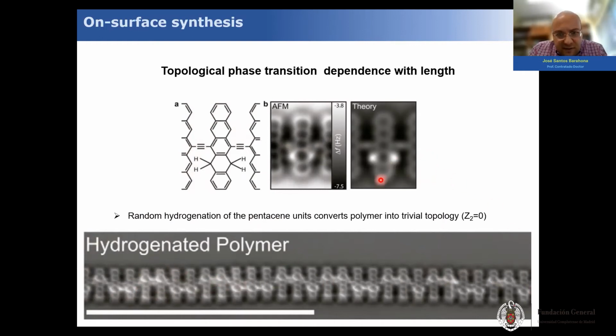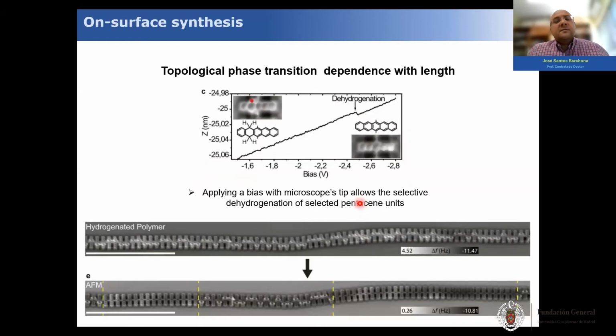As you can see, the hydrogenation is denoted by these brighter spots here, because they are no longer planar, so they are not coplanar with the surface, but they are protruding up towards us, let's say, in the Z axis. Then, by the application of a bias with the tip of the microscope on top of these hydrogens, we can selectively dehydrogenate them, and we can at will engineer these long hydrogenated chains.